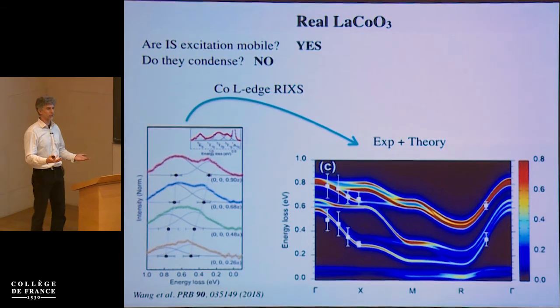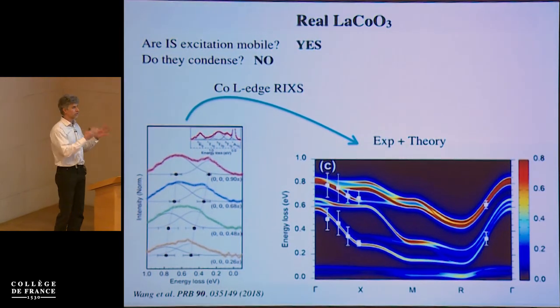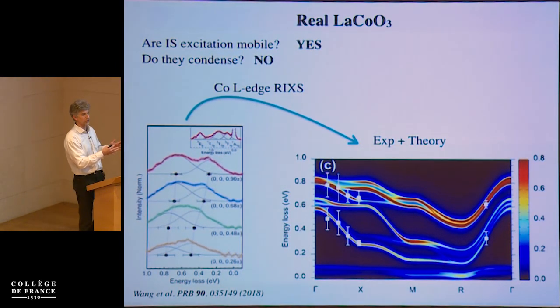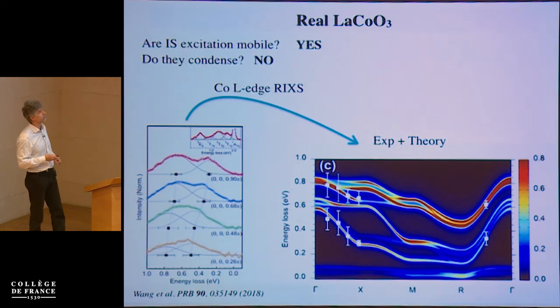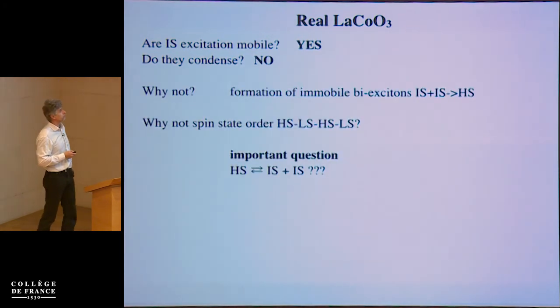Unfortunately, we cannot really probe the most interesting part, the bottom of the band. This is simply a restriction due to the photon energy. This is a measurement at the L edge of cobalt at a photon energy of about 700 electron volts, and you simply don't have enough momentum to probe this part of the Brillouin zone. So this is still an open question.